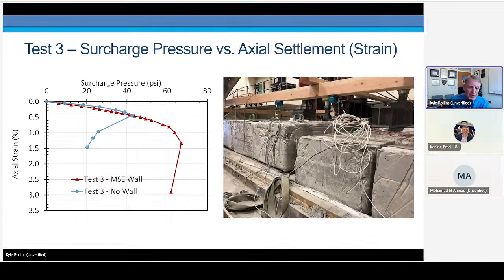This plot shows the axial strain versus surcharge pressure. Once again, the load versus pressure versus strain curves are very similar for the case with no wall and the MSE wall until we get up to about 40-something PSI surcharge pressure. At that point, when we're loading against the free face, the resistance drops off substantially, maybe 1/2 of what it was at the peak, and we start to develop a lot of axial strain.